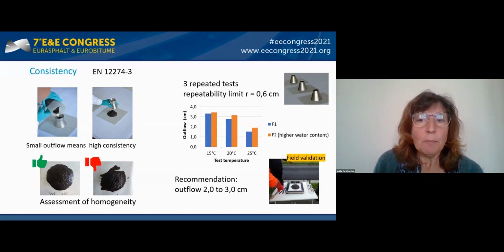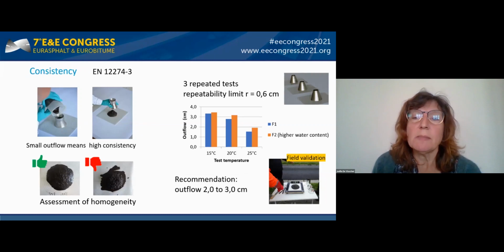So this is a very simple but useful test to optimize the mix for consistency. And it was also verified in the field that an outflow of 2 to 3 centimeters corresponds to an adequate consistency.